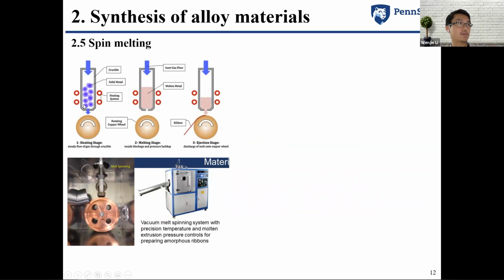And there's another method called spin melting, which can provide an even faster cooling rate. Basically, we load the raw materials inside the crucible, which is made either of quartz or boron nitride, and we heat it up like what induction melting did. After the metal is fully melted, due to the relatively higher viscosity, it will not come out from the hole at the bottom. Then at the ejection stage, we apply inert gas pressure and press out all the molten liquid and let it drop on the high-speed cooled copper wheel, to produce ribbon-type materials.